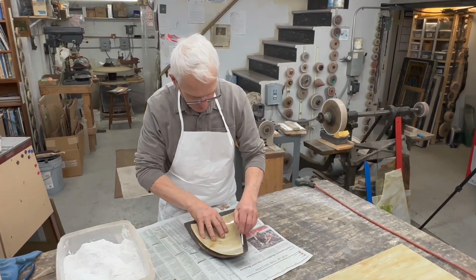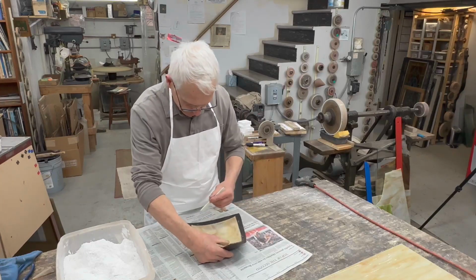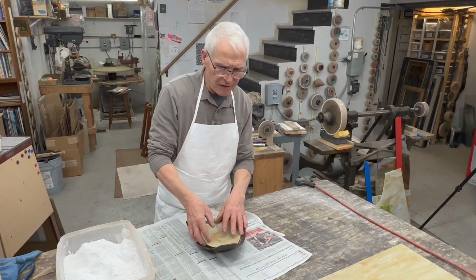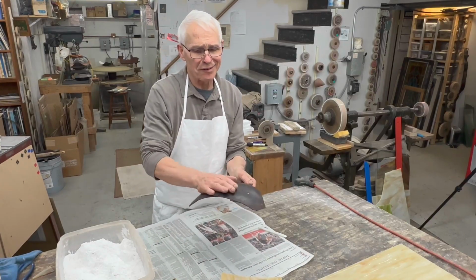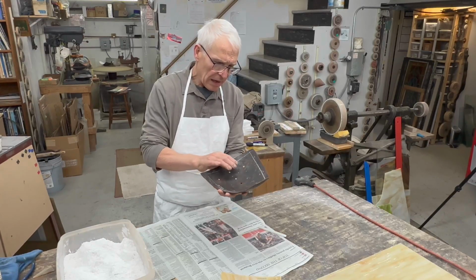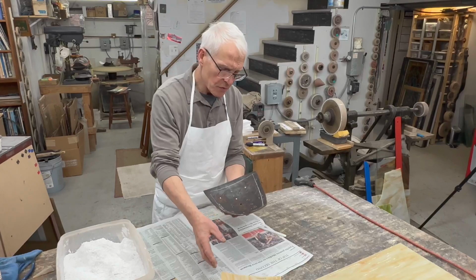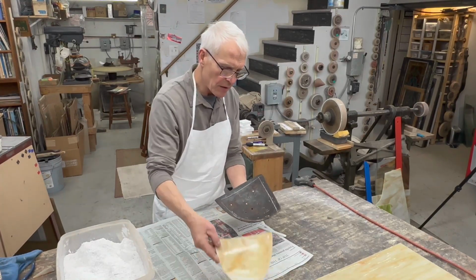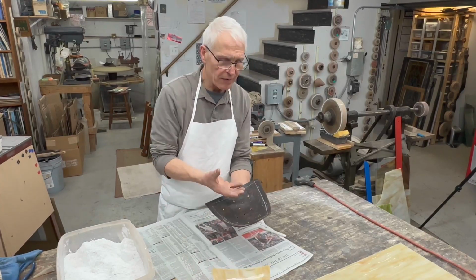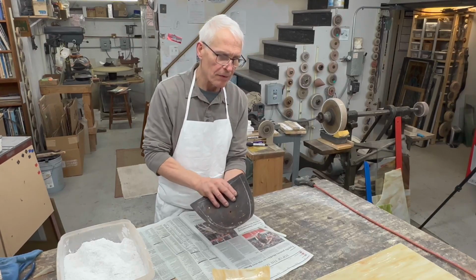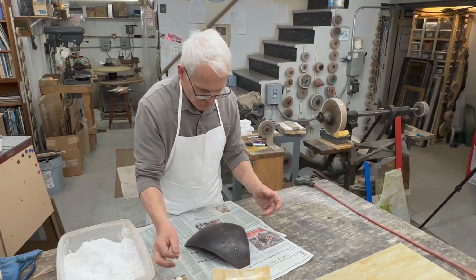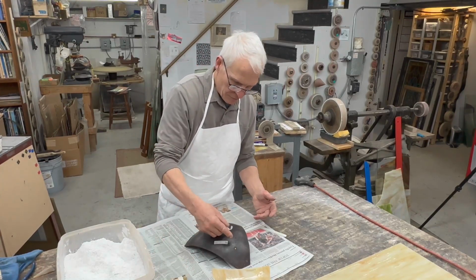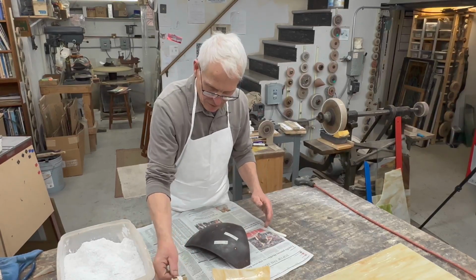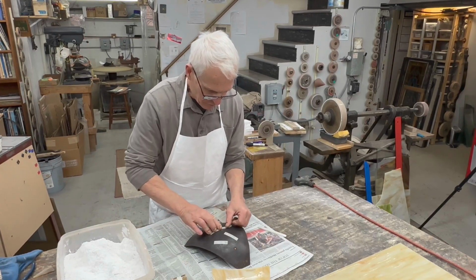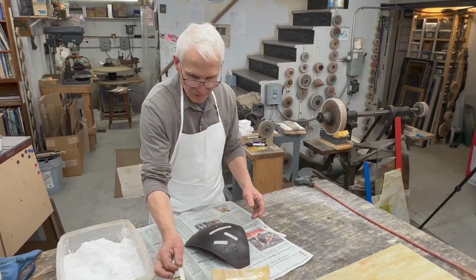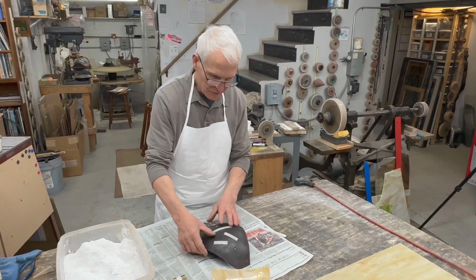Put some reference. This is soapstone, and this metal, it's just steel. There are holes in it because this is like a production mold back in the day, and they drilled the holes in the steel to allow the hot air to escape, so that when the glass was slumping, the hot air didn't hold the glass up and prevent it from slumping down all the way. But since we need to fill the mold with a fill, we're going to tape up the holes so that the plaster slurry doesn't end up going through the holes.